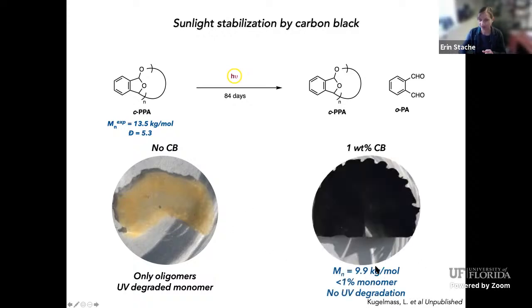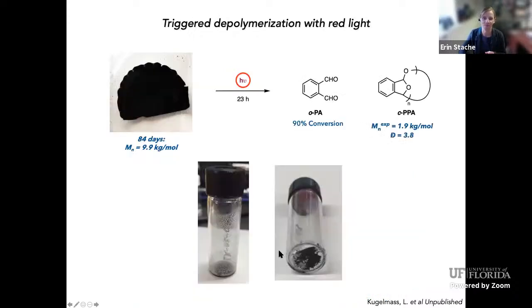With carbon black, however, we've seen a small amount of degradation, but this actually looks pretty good. By the NMR, we see less than 1% monomer, and we don't see any UV degradation products. So the carbon black is actually protecting the polymer from degradation. It's stabilizing it for really long periods of time. This is a very long lifetime for this polymer, just out in ambient conditions. Normally, it's not going to be that stable.